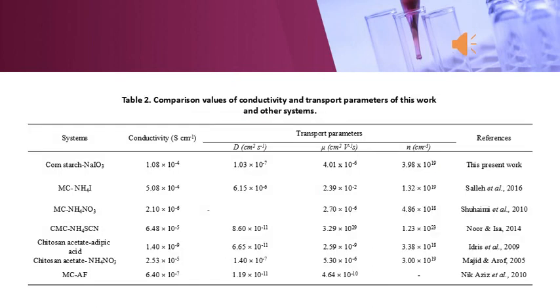Table 2 shows the comparison of the transport properties in this research with other systems. From that, it can be said that the ionic conductivity of this research is one of the highest among the other systems. This is due to the higher values of diffusion coefficient and mobility of ions, which can affect the transport properties of ions and then contribute to the increase in ionic conductivity. So compared to the other works, the values are also related to the diffusion coefficient and the mobility of the charged ions.